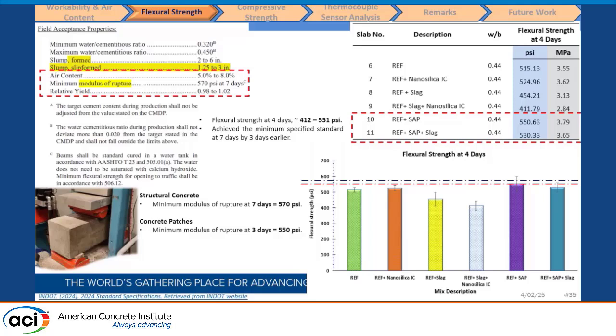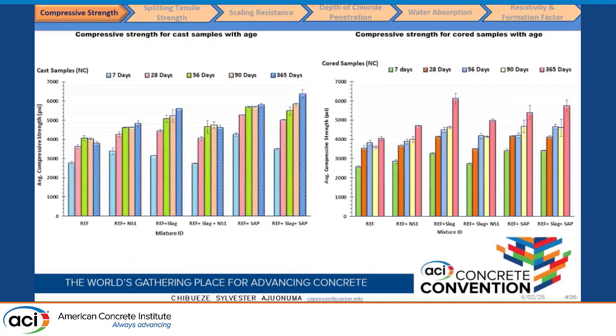And we found that the addition of SAP helped to improve the flexural strength. Also, if you notice the third bar, the mix with 30% slag replacement had a reduced flexural strength, but when we added SAP to it, it also improved the flexural strength. So there's a synergistic effect between SAP and slag in improving the flexural strength, especially at early age. It compensated for the early age strength reduction.